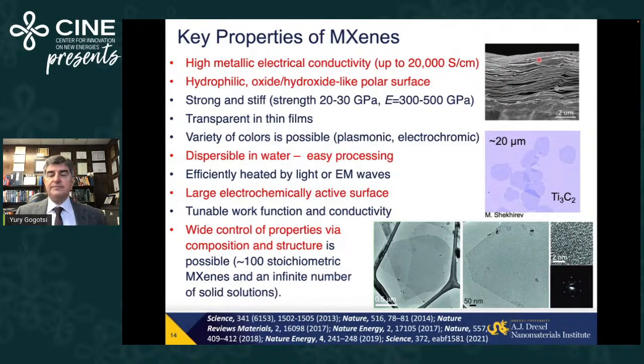And make a film, like a paper, like a graphene paper. You might have seen it, a very popular material right now made from reduced graphene oxide. You can get conductivity, actually nowadays we get over 20,000 Siemens per centimeter. Just for comparison, similar paper produced by reducing graphene oxide will have 10 times lower conductivity, in spite of graphene always being praised for its high conductivity. And the reason is that graphene is a zero band gap semiconductor. You need to create defects, dope it to produce carriers. The majority of MXenes are true two-dimensional metals with a high density of states at the Fermi level, high concentration of carriers. But they're very unusual metals.